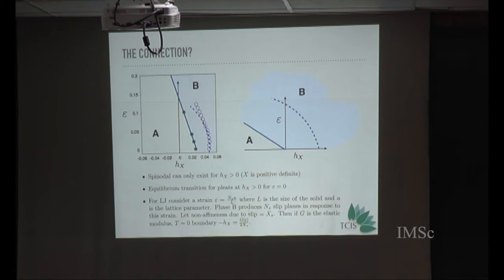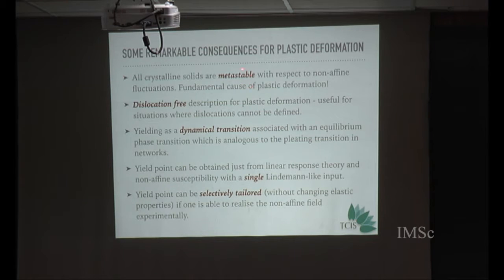It can work only if all crystalline solids are actually in this metastable region. So they are really metastable. This is something sort of dangerous to say. The consequence is that all crystalline solids are metastable because you can always reduce stress by rearrangement, paying only a boundary cost. However, you can make them stable by putting in a field. You can prepare an absolutely perfect solid only if you put in a field or attach bonds to them. That is the only way you can shift the equilibrium line to the right. That is the only way you can go into phase A, but otherwise you are always in phase B.